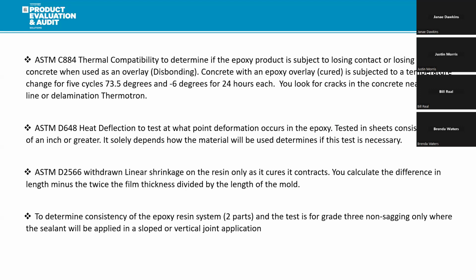Also, to determine consistency of the epoxy resin system, it's in 2 parts, and the test is for grade 3 only, for non-sagging. So if you get an epoxy in and it's for a grade 1 or a grade 2, you won't need to determine the consistency of the epoxy. That's used only where the sealant would be applied in a sloped or vertical joint application, because as you're applying it, you don't want it to sag or run.